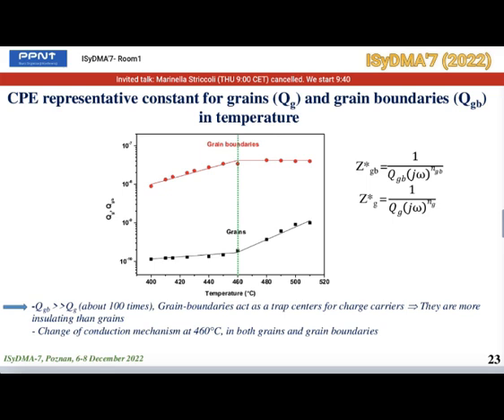We also notice the change of slope here, which indicates a change of conduction mechanism from 460 degrees in both grains and grain boundaries.